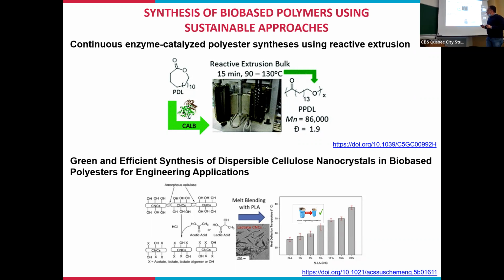So it means that the surface modification, we adapt it in such a way that we have a real improvement. This is an example where we modify in situ the cellulose nanocrystals with lactic acid in a one-shot system. We start directly from fibers and do the modification in order to recover the modified nanocrystals, and by simply dispersing them using an extrusion technique, we can have an improvement.